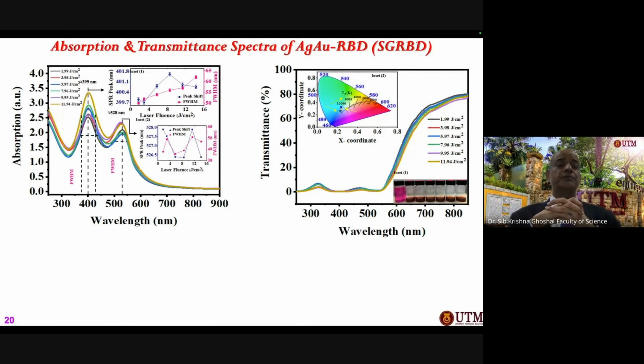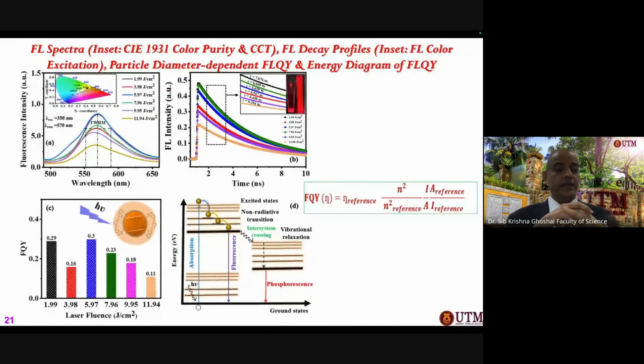So we first make the absorption measurements and look at where the localized surface plasmon absorption is maximum. And we use this maximum localized surface plasmon absorption peak to make the sensing element. And then we have to also look at the transmittance of this kind of material, because if it is not fully transmitted, then we will not be able to propagate the signal. So both transmittance and absorption measurements are necessary for this kind of material.